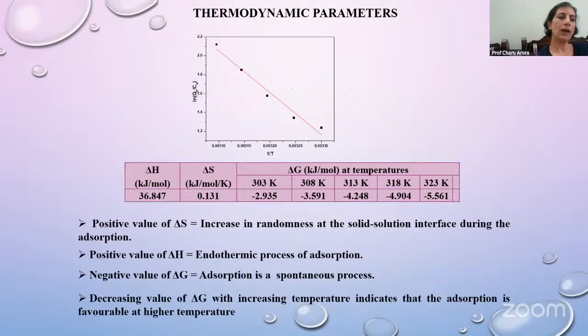These are the values of the thermodynamic parameters. So you can see delta H and delta S are both positive. Positive delta S indicates the increase in randomness in adsorption. Value of delta H is positive, indicating an endothermic process. Negative value of delta G indicates the removal process is spontaneous in nature. And the value of delta G decreases with increasing temperature, indicating that adsorption is favorable at higher temperature.